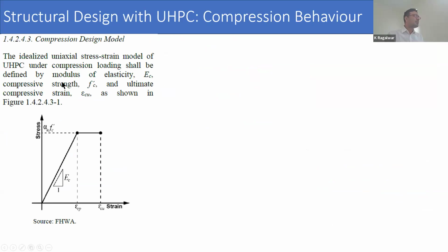So for the compression design model, we know that in Indian codes, we have a kind of parabolic model that we use. In the US, they use a rectangular concrete stress block to define concrete behavior. Here, because of the post-peak behavior of UHPC, the FHWA recommendation is to use a bilinear model. So the first part is a linear model with the strength increasing to factored compressive strength linearly, and then this strain limit is defined by the modulus of elasticity, and then basically we truncate the strength at that level and define it up to the